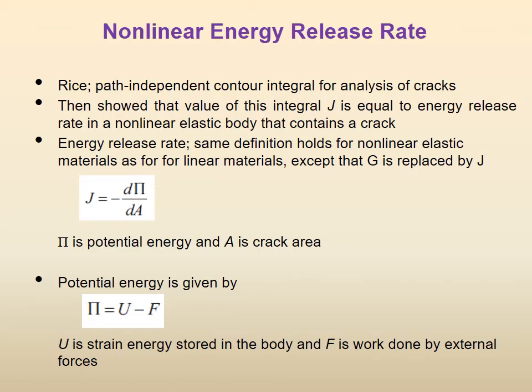Then we started using J, defining J as the nonlinear energy release rate. We told you that G is defined the same way as the differential of the potential energy with respect to A, but that was in the linear area. If we define it in the nonlinear area, then the same quantity becomes J.